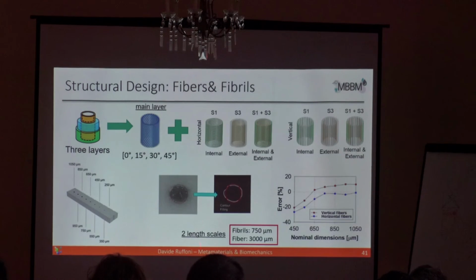And the first thing that we did was to investigate if with the 3D printer we could print fibers and what the minimum diameter of fibers is that we can print. So we tried to print from 250 micron up to 1 millimeter in diameter, and then we did some optical microscopy and calculated the error between the nominal diameter and the real diameter that we would expect. Based on this study, we could say that the smallest fibril that we can print has a diameter of about 750 micrometer with this technique. And based on this, we rescaled all our system.